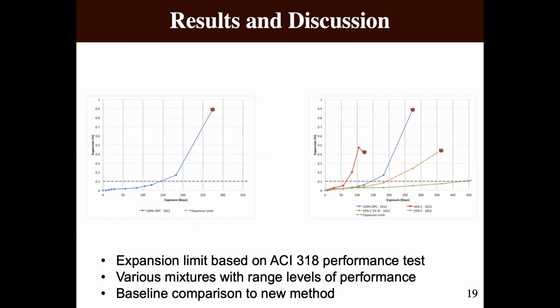And so when we look at just the 10-12 method, meaning we haven't vacuum saturated it, and you look at the control, this is a typical curve that you get from sulfate testing, an expansion curve that slowly begins to progress upward. And once you initiate cracking, then you begin to really escalate the cracking. When looking at variations in mixes, this is the Class C fly ash. Class C tends to perform much worse, particularly because of the chemistry. And then this is a ternary system, and this is the Class F. Class F typically has much better performance. So this is one of the reasons we chose these chemistries, is that it has a variation in terms of performance, right?